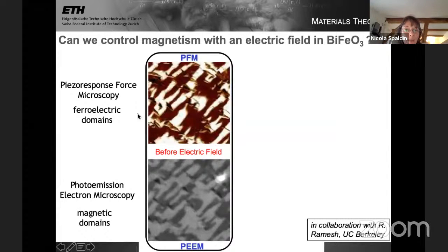It was very exciting. So this is a picture of looking at the surface of a film of the kind that I just showed you. And it's the same area of the surface imaged in two ways, one using piezo force microscopy and one using photoemission electron microscopy. And this is just an as-grown sample before any electric field is applied. The piezo force microscopy is sensitive to the ferroelectric domain. So the brown and the white colors are indicating opposite orientations of the electric dipoles coming out of the surface. And the photoemission electron microscopy is responding to the magnetic domains. So the light gray and dark gray is indicating opposite orientations of the magnetic order parameter. So this is before any electric field was applied.